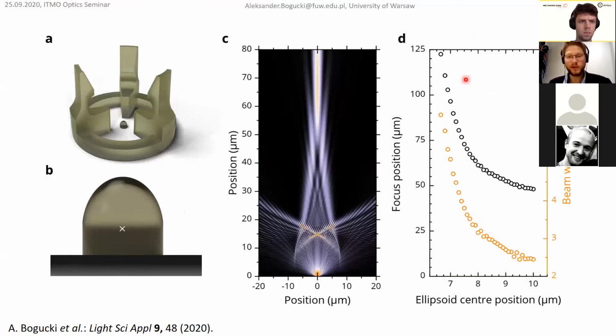So now I'm coming to the end of that part. We can also introduce some modifications to this design. The simplest modification is to raise this elliptical microlens a little bit, and because of that, you will obtain a focus point not at infinity, so not a collimated beam, but a focus in the range of 60-70 micrometers. And when you calculate the beam width and focus position, it means that you can couple to an optical fiber, for example.